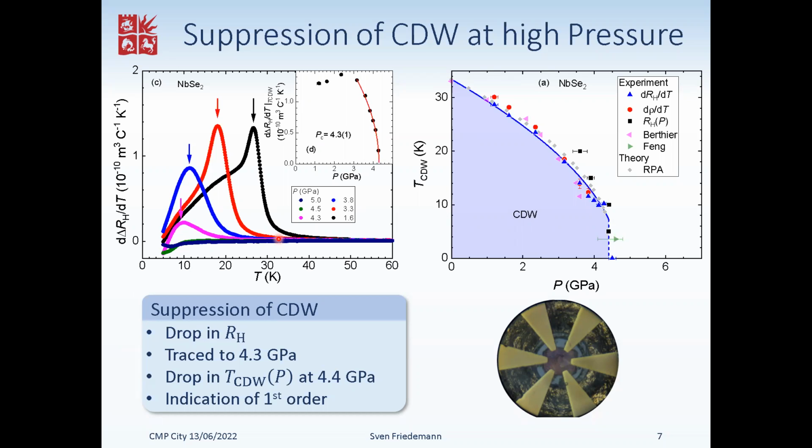So that's why probably, even though we are considering only very small bits of the Fermi surface that are kept out, the Hall coefficient can change dramatically from positive to negative. And in a multi-band system like this, it also depends very subtly on the mobilities of the individual bands, so that it's a weighted average. So from the Hall coefficient alone, it's often difficult to say exactly what's happening to the Fermi surface. But it is a powerful probe of saying that something is happening to the Fermi surface.